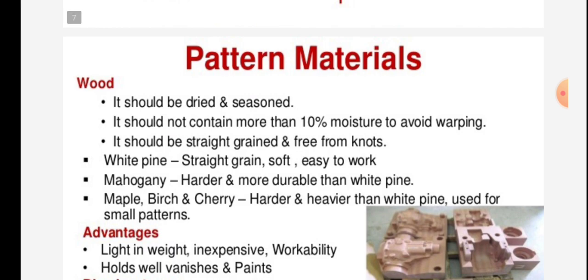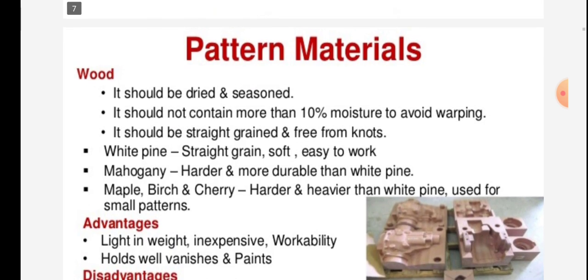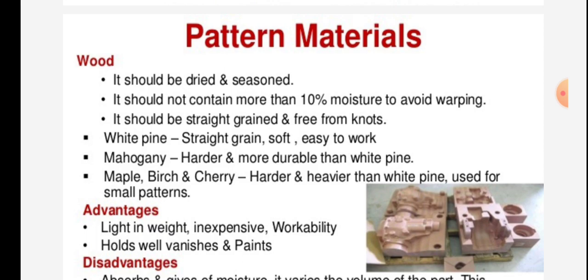Now we will see the materials from which patterns are made. For wood, it should be properly seasoned and should not contain more than 10% moisture, to avoid warping. It should be straight grained and free from knots. White pine is straight grained, soft, and easy to work.